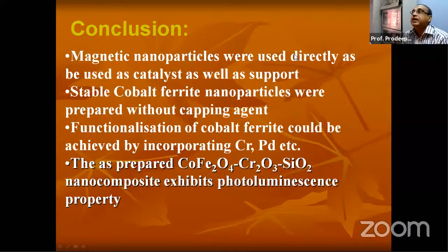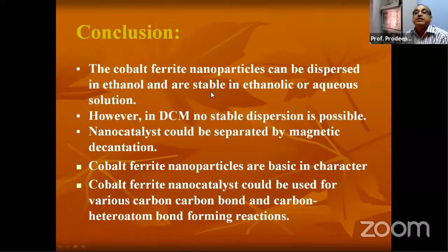And finally, I would like to conclude. Magnetic nanoparticles were used directly as catalyst as well as a support. Stable cobalt ferrite nanoparticles are prepared without capping agent. Functionalization of cobalt ferrite could be achieved by incorporating chromium, palladium, copper, etc. The cobalt ferrite chromium oxide SiO2 nanocomposite exhibits fluorescence property. The nanoparticles can be dispersed in ethanol and are stable in ethanolic and aqueous solution. However, in DCM, no stable dispersion is possible.